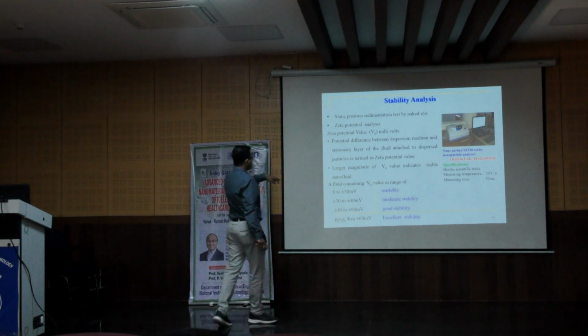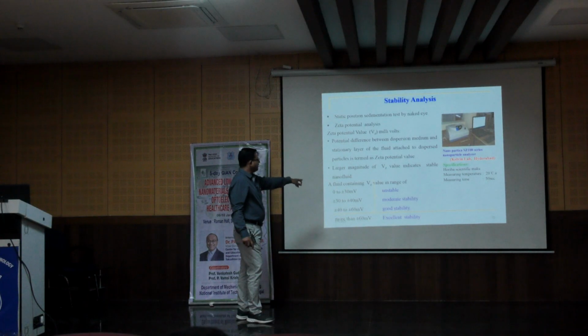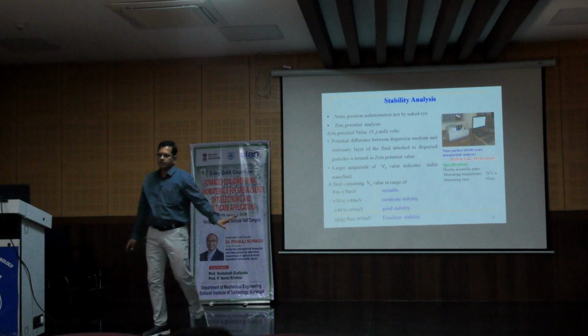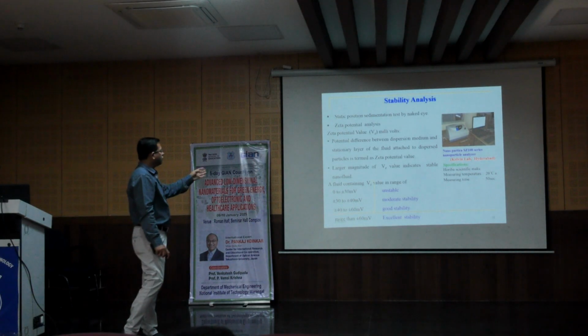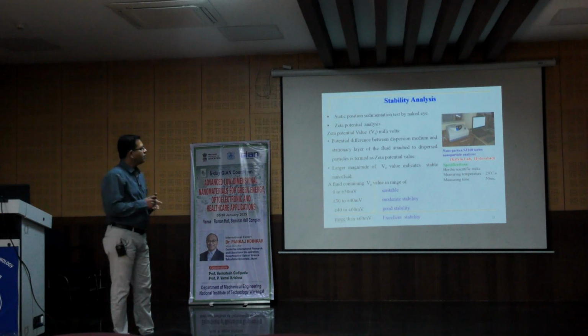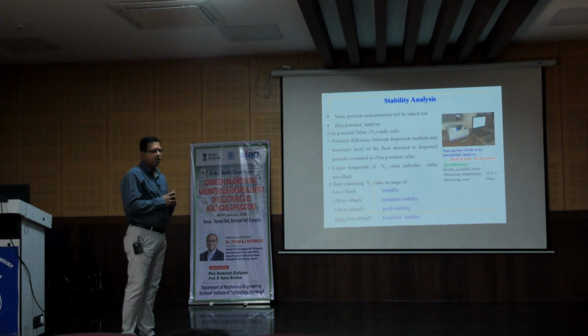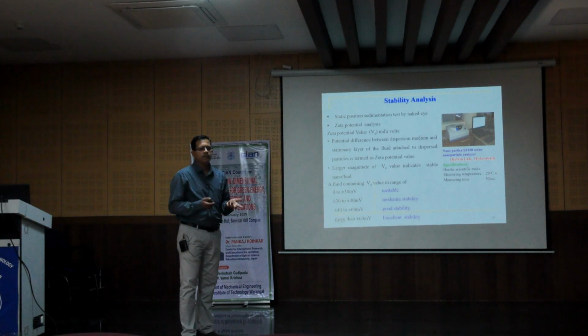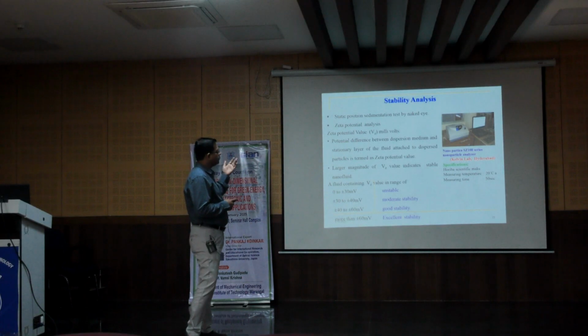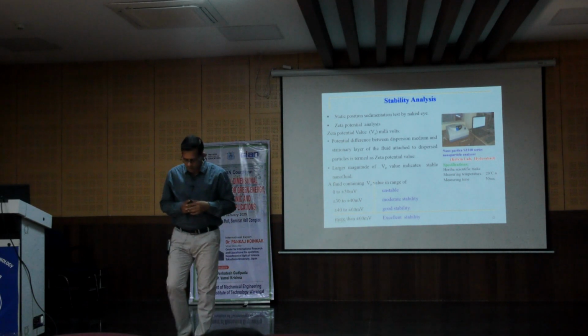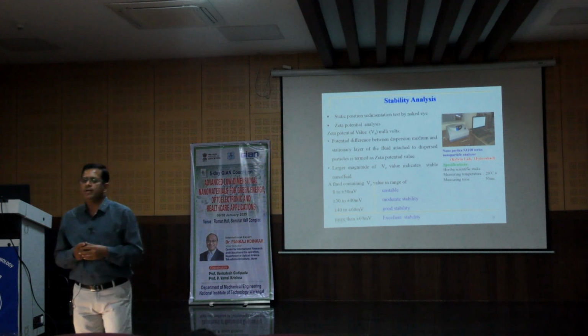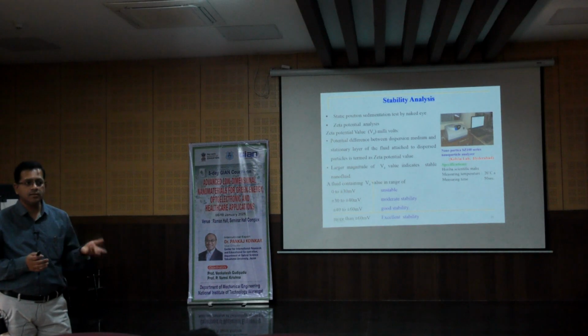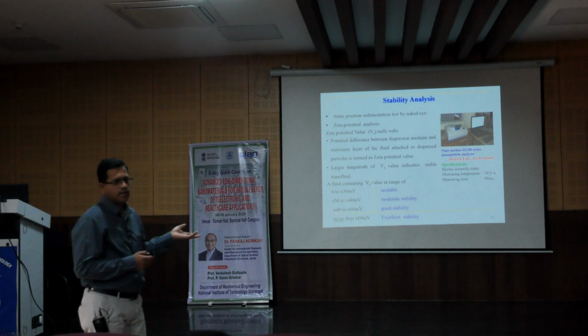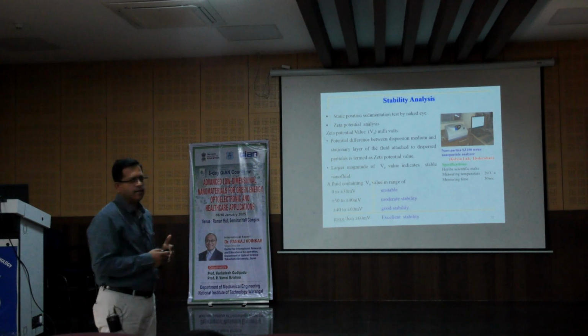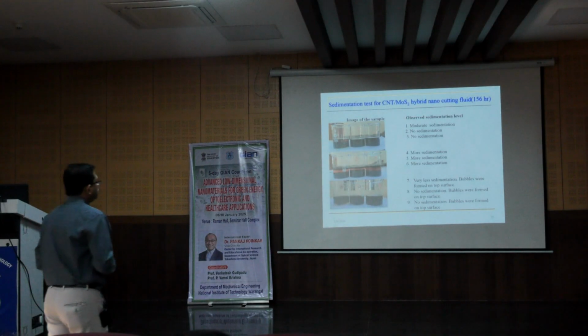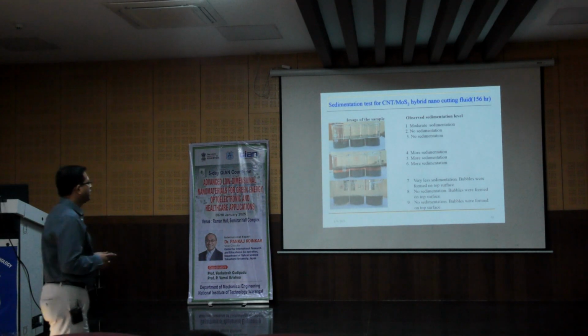If the zeta potential value is 0 to 30, then this nanofluid is unstable. If it is 30 to 40, then it is moderately stable. If it is 40 to 60, the stability is good. And if it is more than 60, then we can say excellent stability. So after preparing this, we can check with the analyzer and see what the stability of this particular nanofluid is. If the stability is not good, then maybe we can try another percentage of mixing or another surfactant, etc. Right?